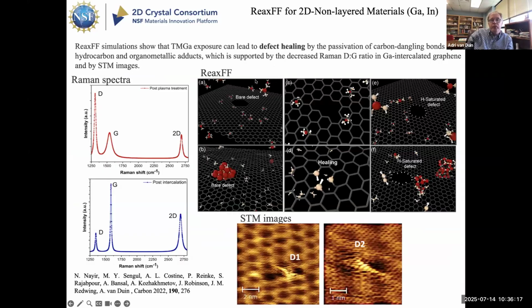What's also very interesting is that one of the goals of this work is to deposit the gallium underneath the graphite. To make that happen, the experimentalists shoot holes in their graphite with oxygen. They make holes on purpose so that the trimethyl gallium can get through. They observed experimentally that it works, but for some reason it stopped working. What we found in our simulation is that the trimethyl gallium can actually repair those holes. Over time, the trimethyl gallium precursor can dissociate on the edges of those holes and heal them. The concept doesn't work anymore because the holes close themselves and the gallium stops depositing in the subsurface. Now the experimentalists know that they pretty much have to recreate their holes every now and then with oxygen plasma. So this really helped explain many issues in the experimental deposition of these materials.